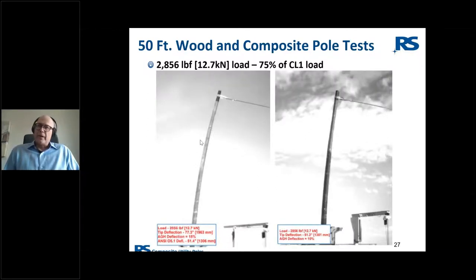So here we are at 75% of class one load, or just shy of 2,900 pounds. And the tip deflection is 77 inches on the Western Red Cedar pole, which is about 50% more than the predicted ANSI value of 51 inches, and that's 15% of its above ground height. And on the right, the RS composite pole, we have about 51 inches. So again, trending just along that ANSI mean value line, and that's 10% of that composite pole's above ground height.